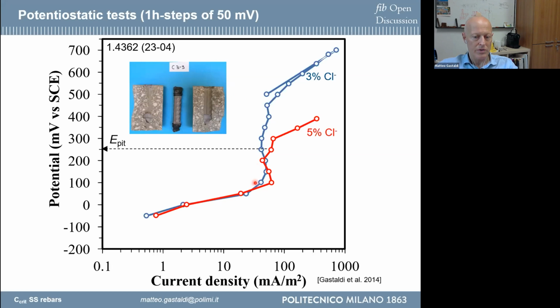For example, you can observe that if the amount of chloride is 3%, you have no corrosion, and it is also observed at the end of the test that there is no corrosion. With 5% of chloride, you start to have a change in the diagram, and this indicates the initiation of corrosion. And then you can observe that you have an increase of the current. This is the parameter that is measured in electrochemistry. It's not so important, but this increase of current means that you have initiation of corrosion. This is also detected at the end of the test.